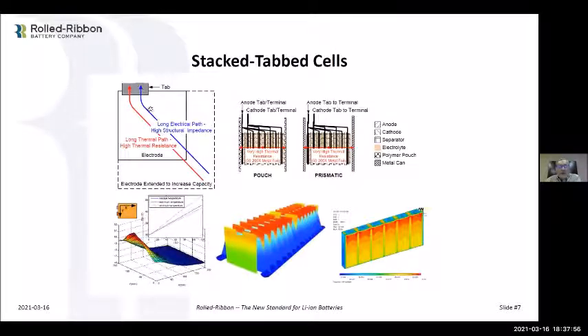In a stack tab cell, what you have is sheets of electrode. What we do in a stack tab is we create a sheet, and we have the tab, and we weld that on the end, the corner in here, for one electrode, one polarity, and then on the opposing side, we do that for the other side. And what happens again is the electrons have to travel across the sheet out to the tab, and that's where they exit the cell. And heat has to do the same thing. It's the only way it gets out.